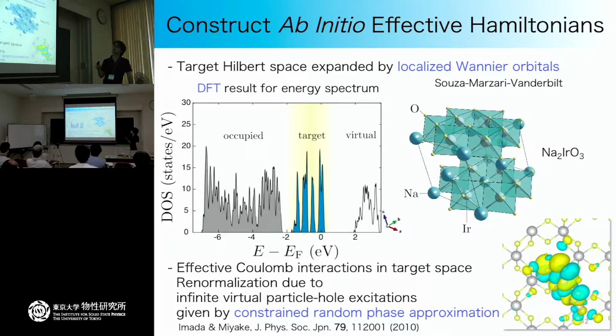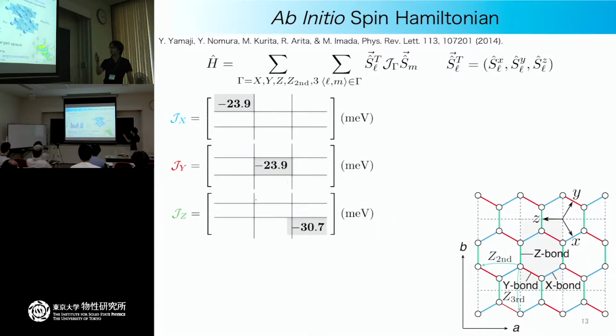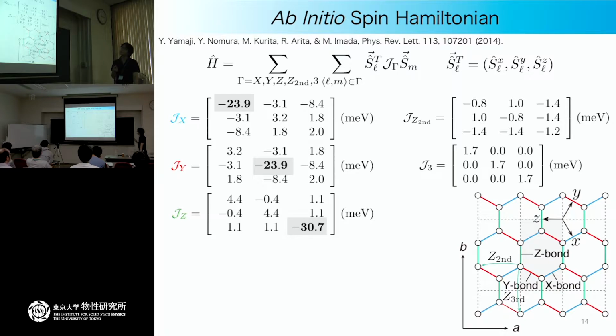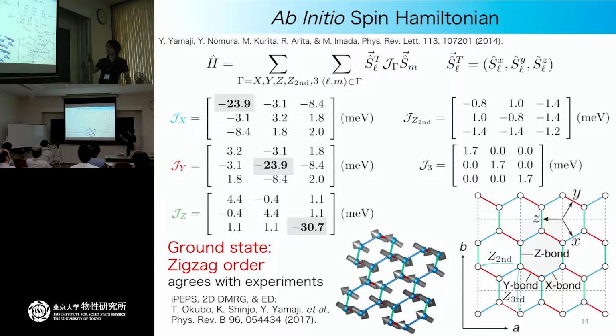There is some way to construct the effective spin Hamiltonian starting from the DFT theory and constructing the t2g Hamiltonian. And if you take the strong coupling limit and do the second-order perturbation from the strong coupling limit, then you can derive the effective spin Hamiltonian for this system. And this is our result for the ab initio spin Hamiltonian for the sodium iridium oxide. Here there are several couplings. And actually speaking, this shaded coupling is the dominant coupling, and it's nothing but the Kitaev coupling. This coupling is dominating in this ab initio effective spin Hamiltonian.